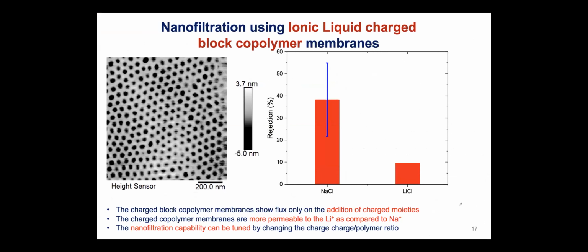I'll just spend one or two minutes because I think my time is almost up, that we can separate ionic liquids. So for lithium ion batteries from brine, which is sodium chloride, there's a 4% lithium chloride carbonate and so on dissolved in brine. And how do you separate it? Well, now you don't extract the ionic liquid. You actually have the brine solution go through the ionic liquid in the block copolymer membrane. And you can see we're getting 40 sodium chloride rejection compared to lithium chloride. In fact, now we have hit more like 70. This is an old slide.